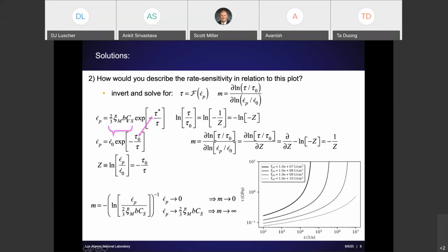okay. So multiplied by the shear wave speed. If you multiply all these things together, you'll find that that provides some upper limit of what plastic strain rate we can accommodate within the material given that particular value of the mobile dislocation density. So that's what epsilon dot 0 represents. That's an upper limit for the plastic strain rate we can accommodate according to this model.